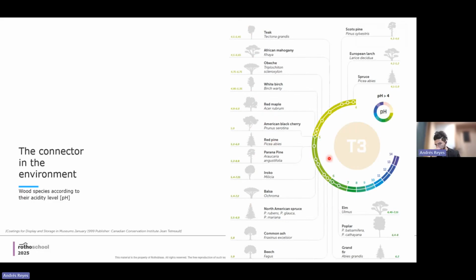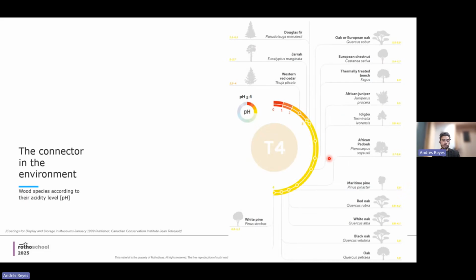We did, in the Smart Book, a sort of database of the pH of the species, so that you can easily identify, by knowing the species of the wood, which one is T3 or T4, so more or less aggressive when exposed to moisture. So in T3, we generally find the most common species: spruce, larch, and pine. While in T4, you generally find hardwoods like oak. Oak is very aggressive, but you also find Douglas fir. Douglas fir, when exposed to moisture, has an aggressive environment inside, and thermally modified beech as well.